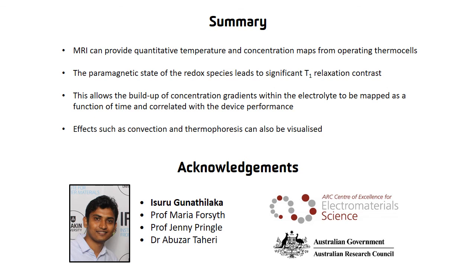And we've seen in these images the build-up of concentration gradients within the electrolyte, and we can map that as a function of time and correlate it with the device performance and other factors such as changes in the external load or changes in the temperature gradient. And it's important to also take into account effects that can occur in these systems such as convection and thermophoresis, which we can also visualize.